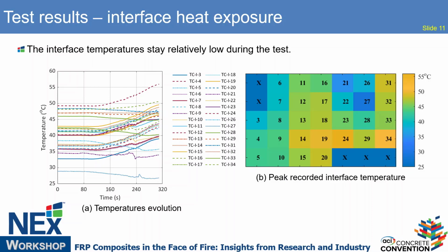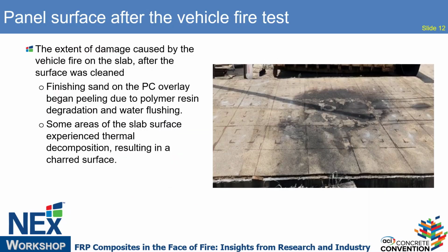So this is a slab after the vehicle fire test, and we washed it to make it look better. We found that the finish sanding, because all the overlays have finish sanding on the surface, on the polymer concrete overlay surface has peeled due to polymer degradation and the water flushing. And in some areas, especially those under the vehicle, the slab experienced thermal decomposition, resulting in some charred surface.